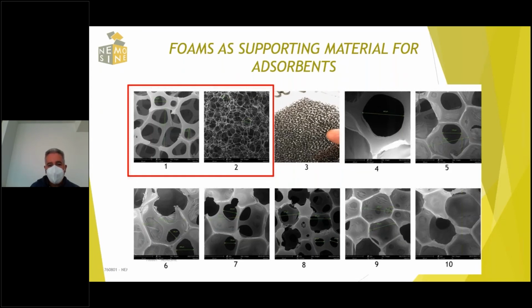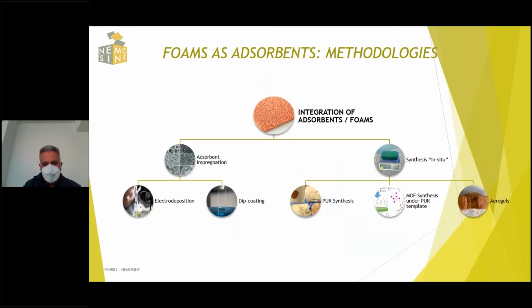Foams 1 and 2 are very clear examples of open cell foams. We can see in these micrographs that very easily, if we put the MOF materials on the sides, we can have a good diffusion of the gas through these foams, maintaining a good supporting material for the deposition of the MOF materials. The important thing is to define how to introduce the MOF materials inside of these foams, which I named the integration of the adsorbent on the foams.